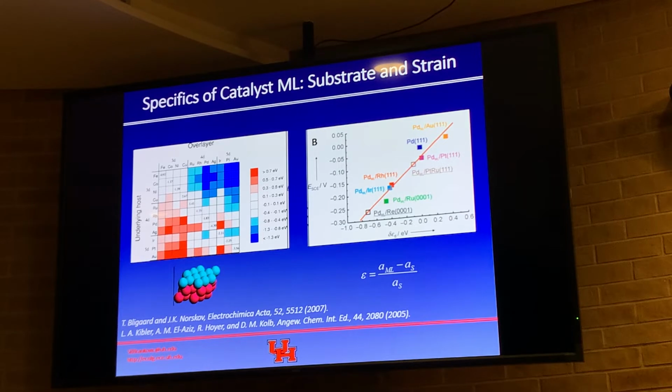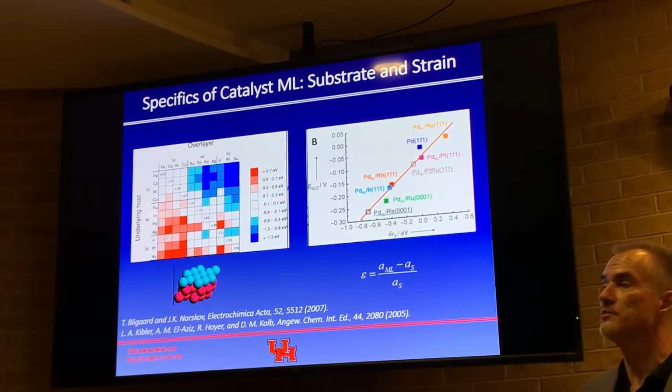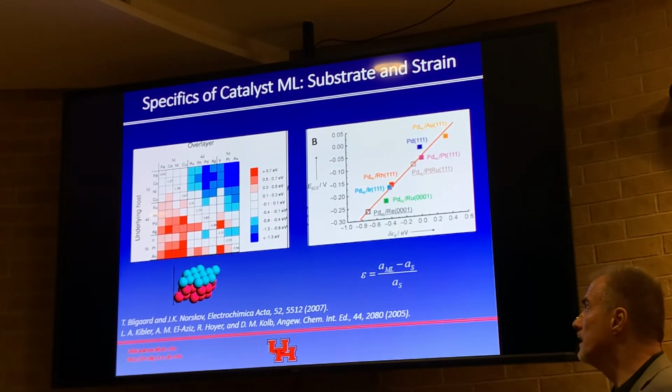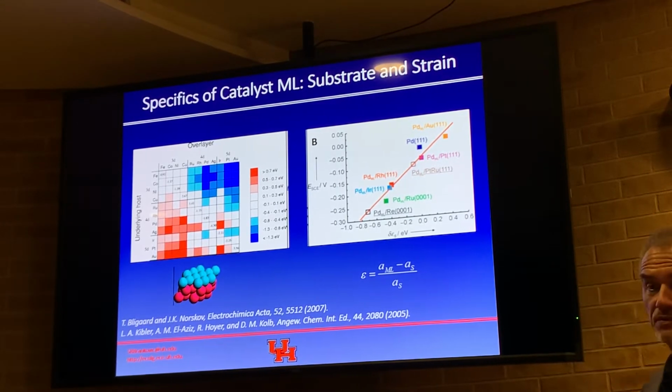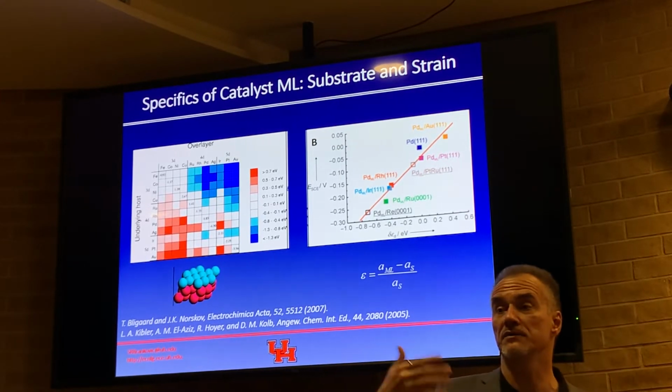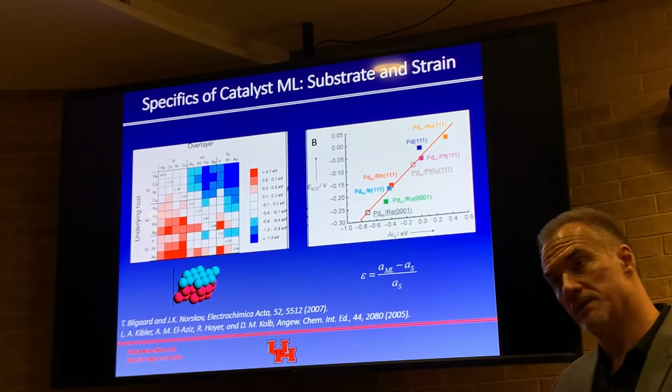White means not really a big change. Now, why is that important? Because if you put the monolayer on different substrate, due to the electronic effect and some other things like strain, you can actually tune the activity by the choice of substrate and that monolayer, and you can make the monolayer more reactive. If you see red, that means more reactive, meaning higher activity of the catalyst,